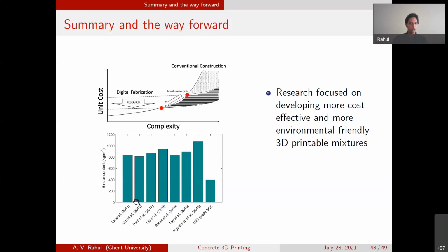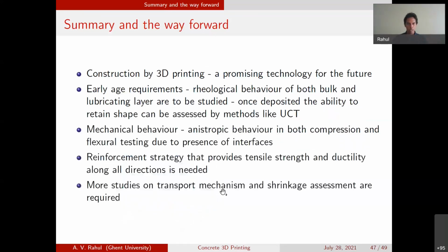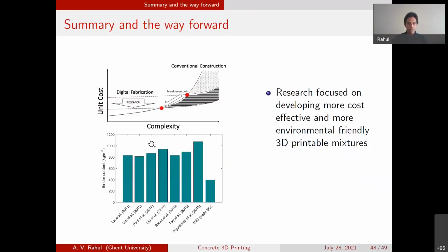And to show a comparison of the cost, the binder content that we require in 3D printing, because the binder is the most expensive component in printed concrete, you see that it's relatively quite high if you look at all these publications, which use relatively high printable concrete. But if you compare it with an M40 grade SCC, for example, you can see where we stand here. It's about 50% higher when you compare it with conventional concrete. So, research in this direction, looking at optimization. Once we understand these aspects in more detail, can we work on strategies to develop more cost-effective printable concrete? This is a need for research.